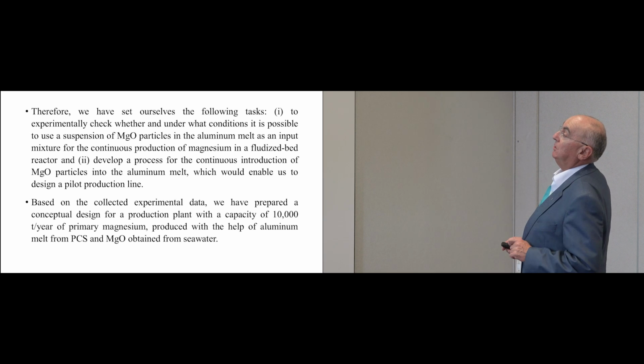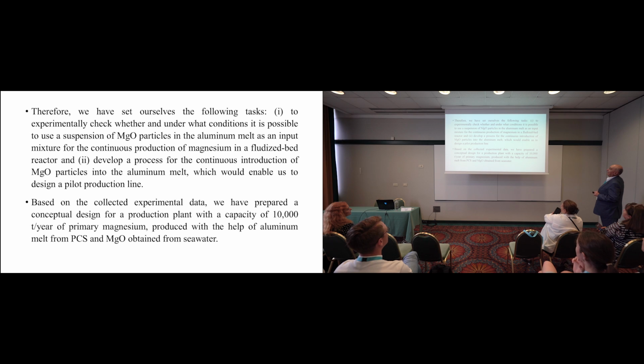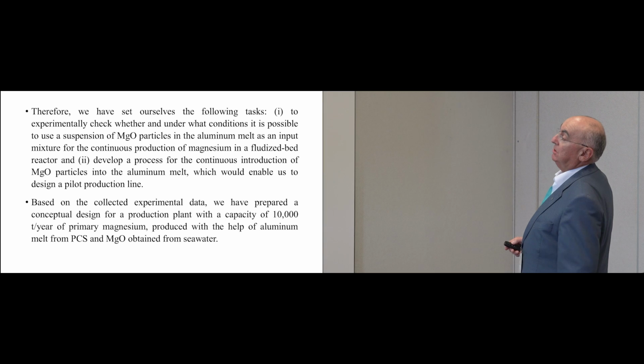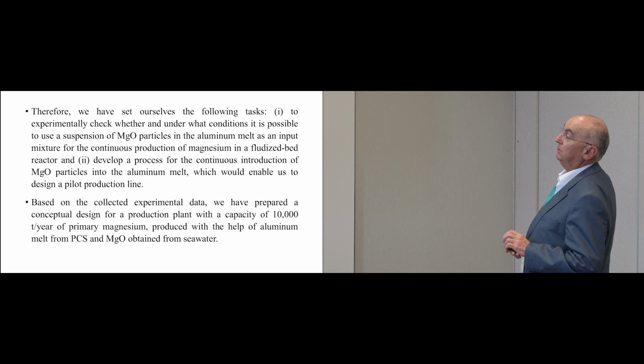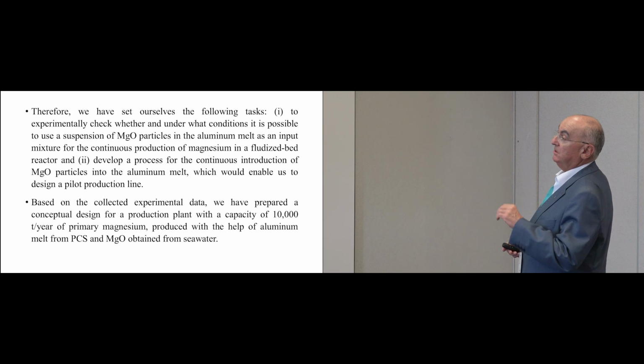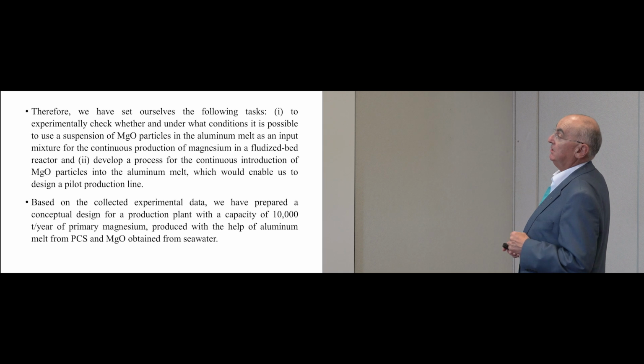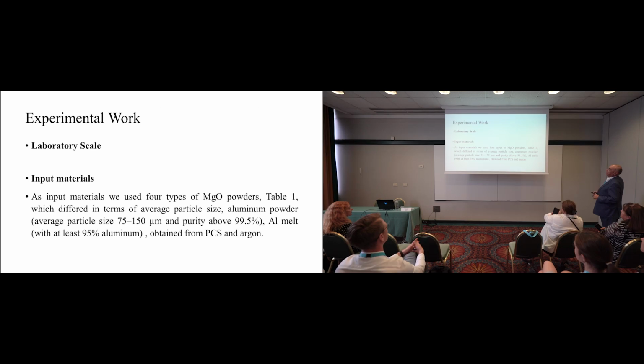So we are looking for continuous production, and of course we try to develop it even on pilot scale. The first part we observed in the laboratory. The second part was on a pilot scale. The continuous introduction of magnesium oxide particles into the aluminum melt, because we recognized this would be the most critical step in such a reduction. So I will try to explain very shortly our experimental work.